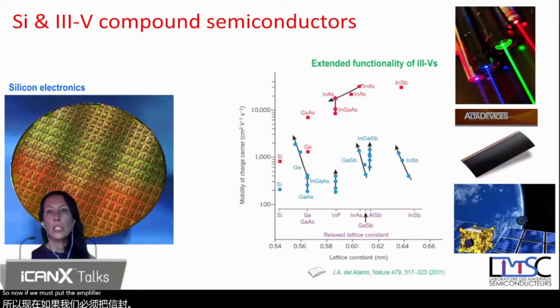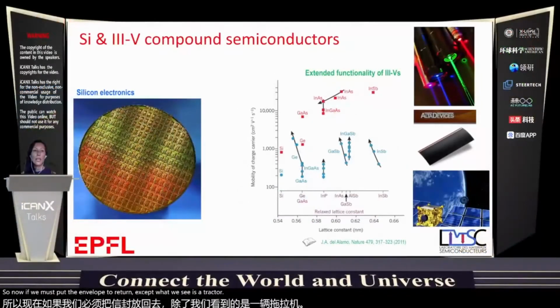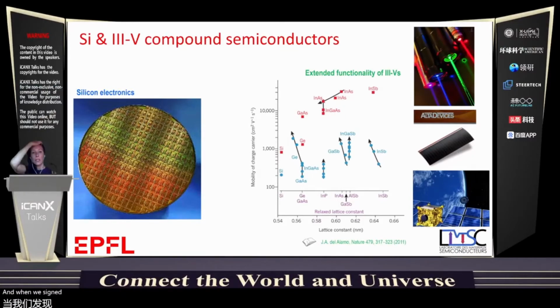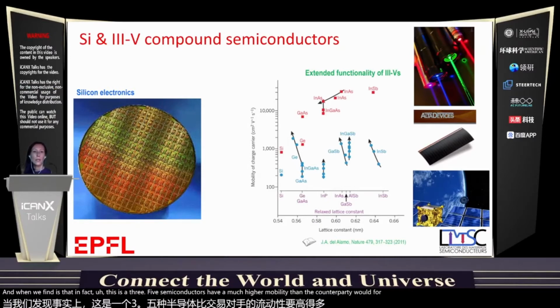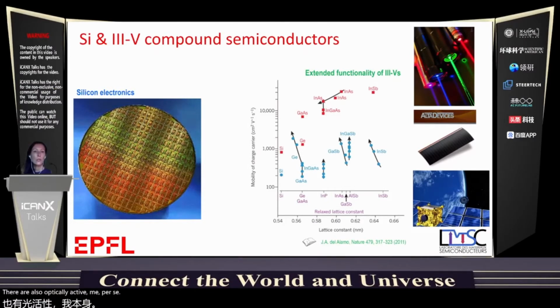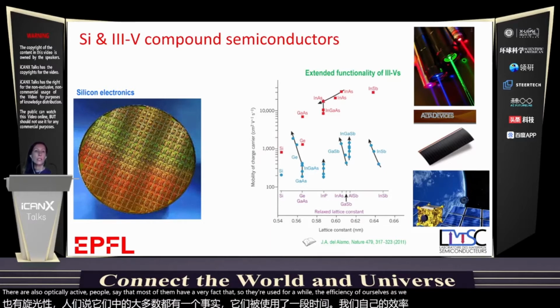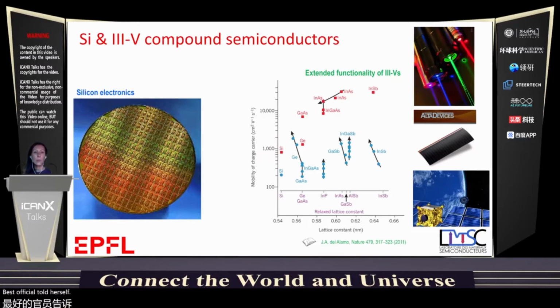Now if we move to the realm of optoelectronics, on the right you see the charge carrier mobility of III-Vs compared to group IV, which are here. What we find is that these III-V semiconductors have a much higher mobility than their counterparts in group IV. They're also optically active because most of them have a direct band gap. So they're used for ultra-efficient solar cells, as you see on the right, the most efficient solar cell is from Alta Devices, and also for lasing and LEDs.